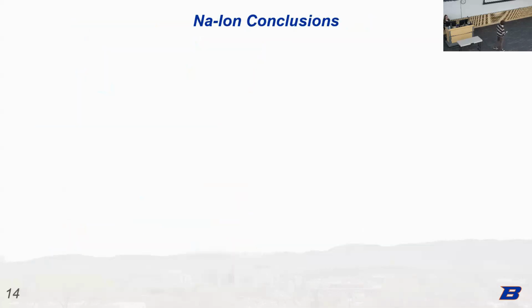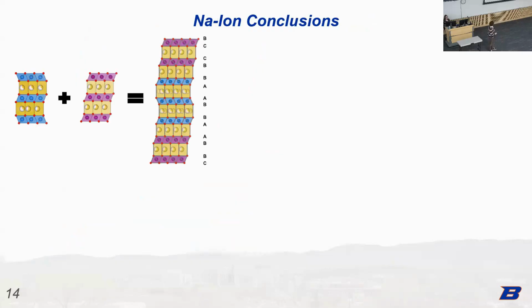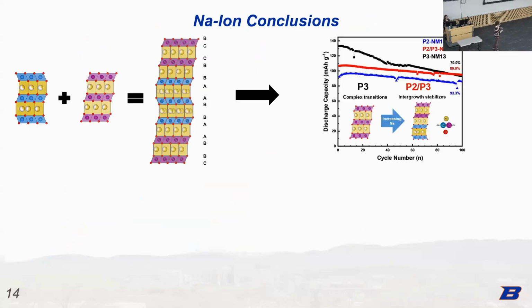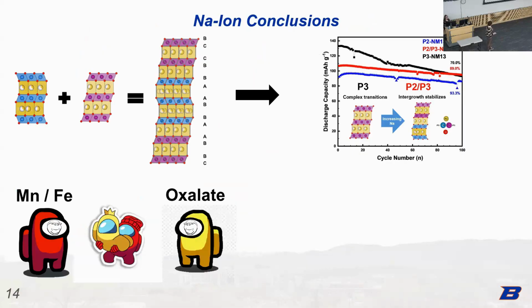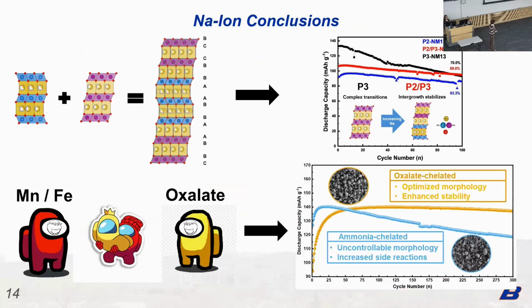So in conclusion, what I effectively have done during my research is I asked myself, if I combine two phases, what do I get? And I get improved cycling performance via synergistic effects between these two structures. And if I'm able to find a more harmonious chelating agent with the oxalate, with the iron and manganese, I'm able to achieve a much more optimized morphology and an increased stability of the cycling of my battery.